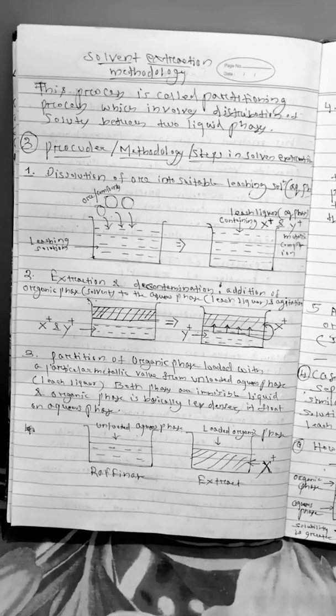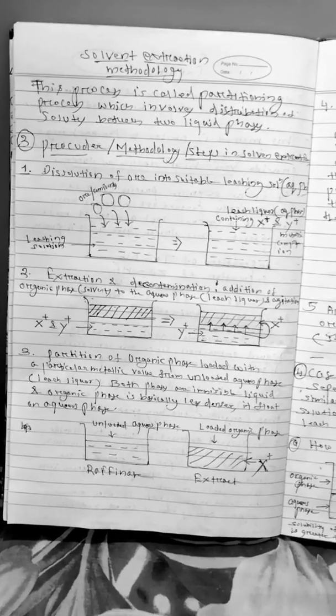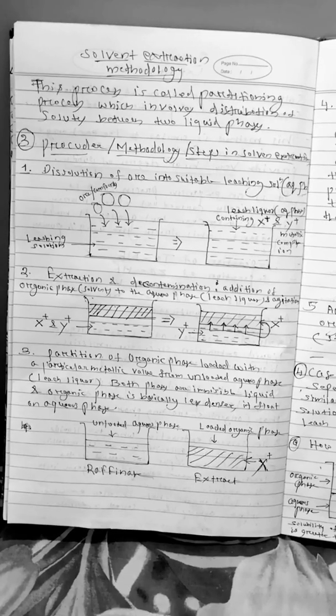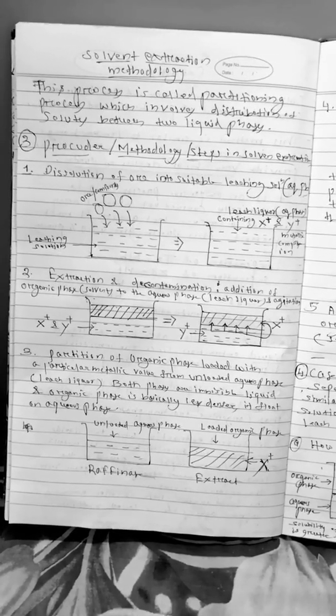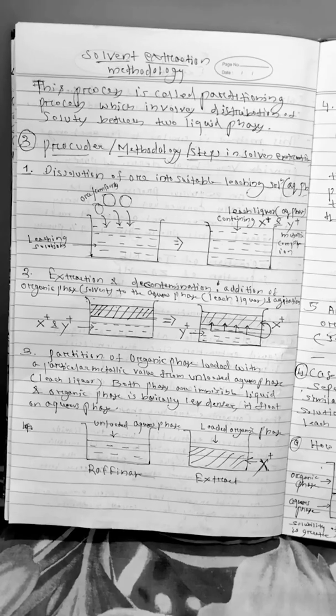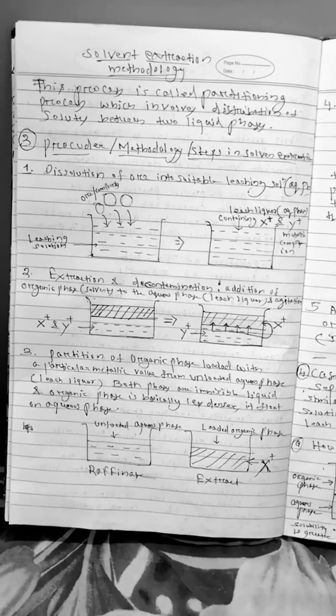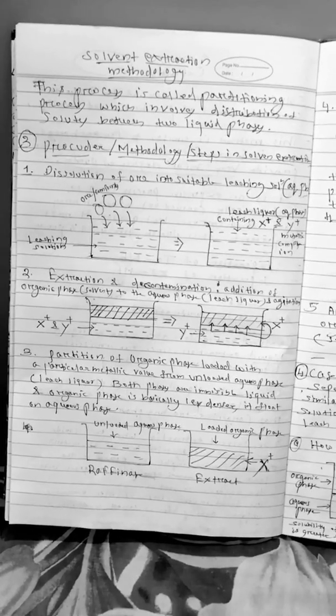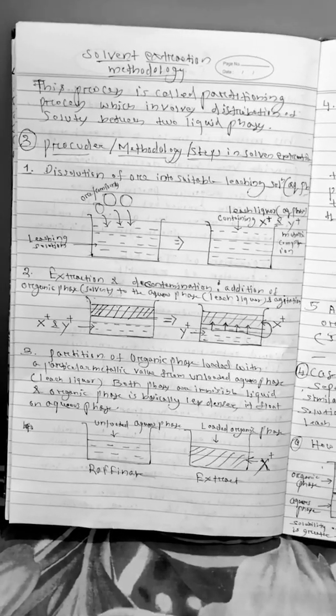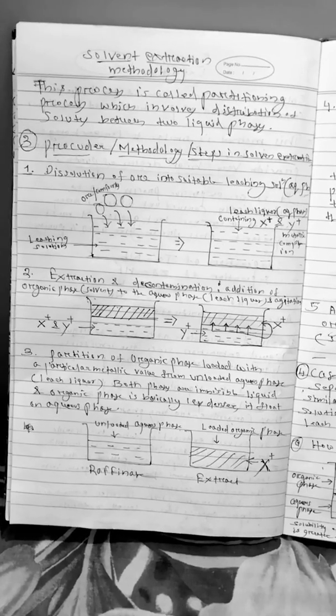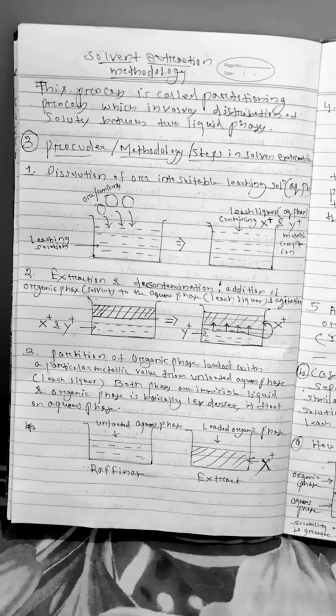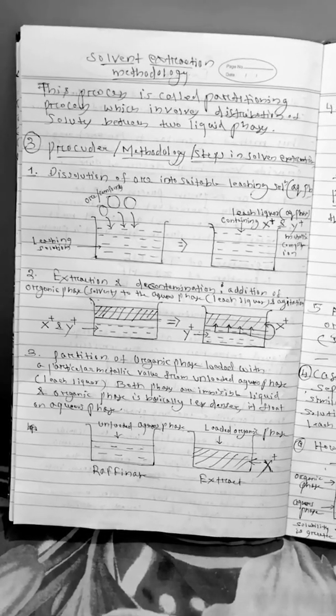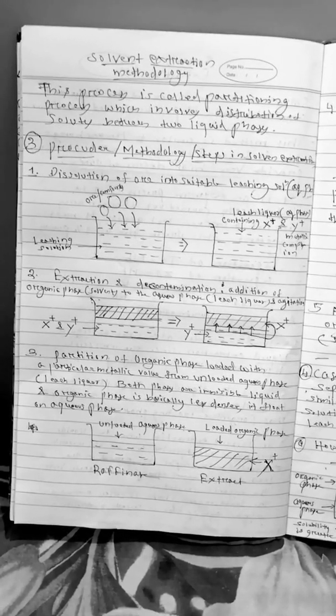The first step in the solvent extraction is the dissolution stage where we dissolve our ore into a suitable leaching solution. Our leaching solution is our aqueous solution. So during leaching what happens if two or more metallic values are of similar chemical behavior they get soluble into this leaching solution. So at the end of this leaching process we'll get a leach liquor containing two or more metallic values.